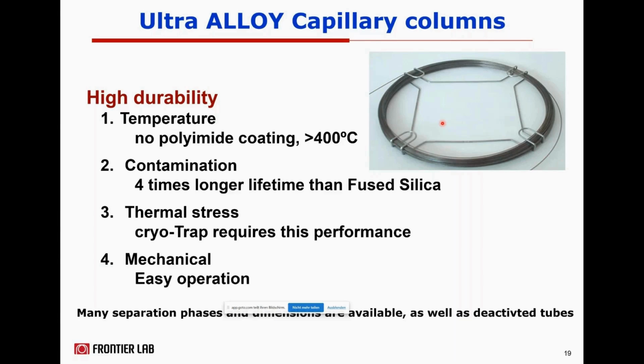And that also makes it possible for our cryotrap, which goes down to minus 196 degrees Celsius, to be applied, and this requires this performance. Other fused silica columns would be damaged, would be broken. Also mechanically, it's very easy to handle and to cut and so on. And we have many separation phases and dimensions available, as well as deactivated tubes, for example, the EGA tubes.